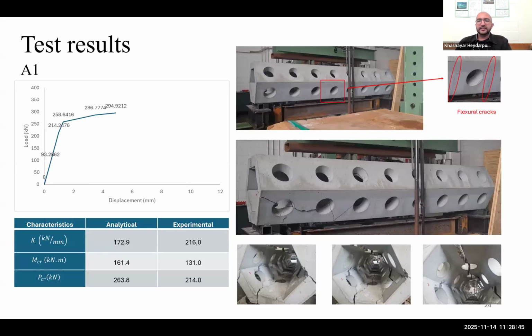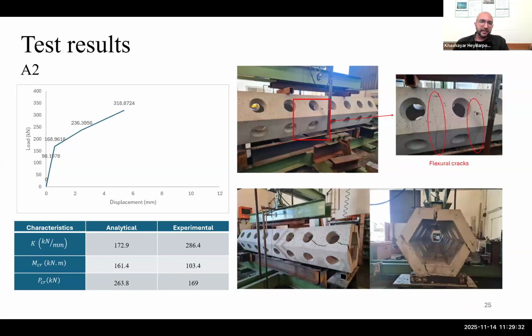Under the 4-point bending test, here we present the test results for each of the specimens, and for mostly all of them the first flexural cracking occurred, and it started from the tensile fiber at the bottom flange up to the mid leg. And the sudden brittle failure of the specimen at the end in the failed mode represents a premature shear failure that occurred at one end of the specimen, where the shear is maximum and the transfer of pre-stressing is minimum. And the same scenario was observed in all other specimens, although with different cracking and ultimate load capacities.